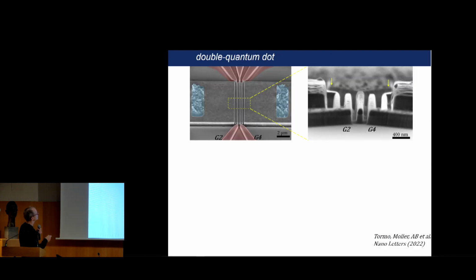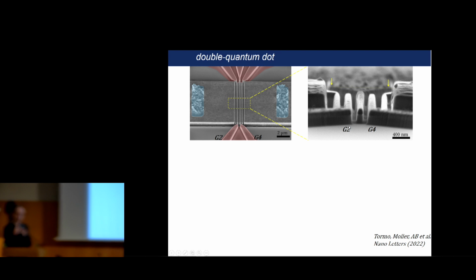So this is the device. The pointer, I still don't understand, sometimes the arrow is coming out and sometimes not. So the white line that you see here is the nanotube. Here in this region, the nanotube is suspended. And if you look at this device with a larger zoom and with a different angle, you get this. And here you can see perhaps at this level the nanotube, but you can barely see it. So don't worry if you don't see it. But the nanotube is here. And we have 5 gates here in order to define the double quantum dot qubit by electrostatic means. Okay?